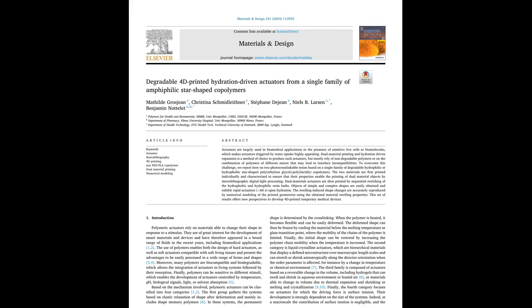with the hydrophilic resin swelling up to 176% in mass and 226% in volume, while the hydrophobic control showed minimal swelling. These swelling differences were exploited in dual-material stacked cylinders with stable interfacial adhesion, producing bending into goblet-like shapes upon immersion in water. More complex dual-material geometries with oriented hydrophilic bars enabled controlled bidirectional curling confirmed by experimental observation and numerical modeling.